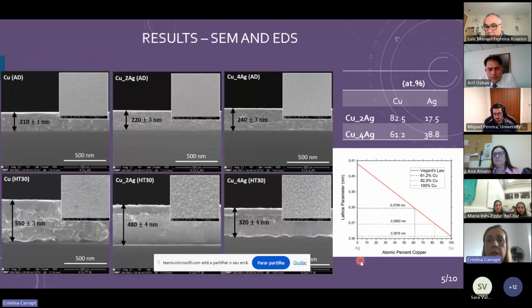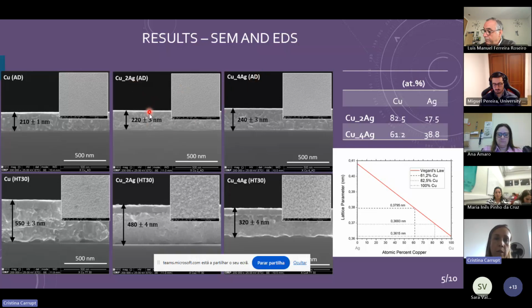The first results. The films were characterized for morphology using SEM, and we can see that the silver content promotes an increase in the thickness of the films. Due to the lattice parameter, according to Vegard's law, when we have an increase in the silver content, it promotes an increase in the lattice parameter. So we can see here a little increase.